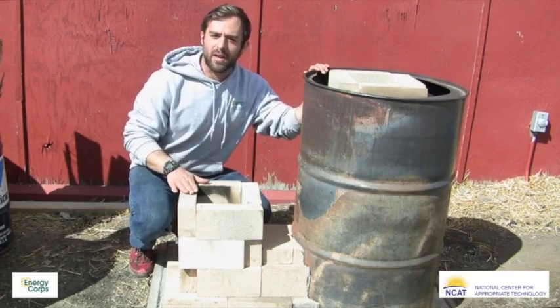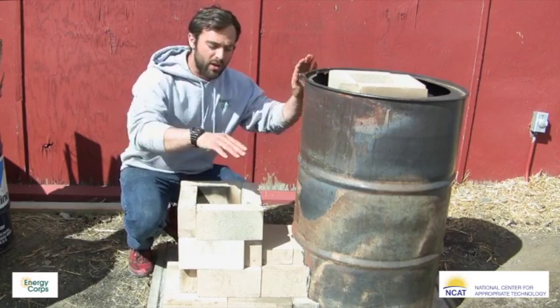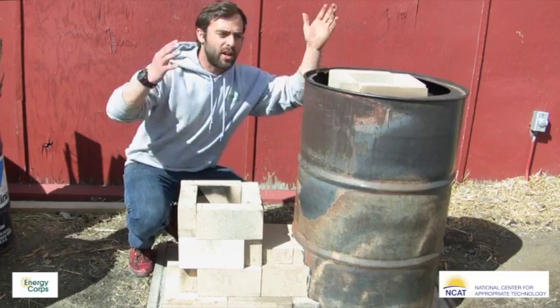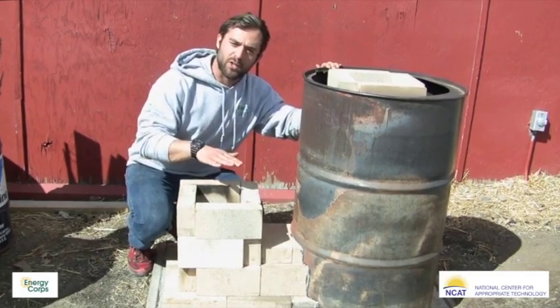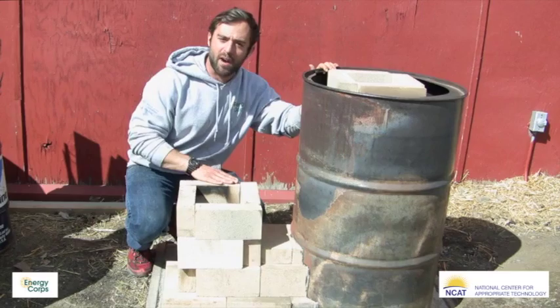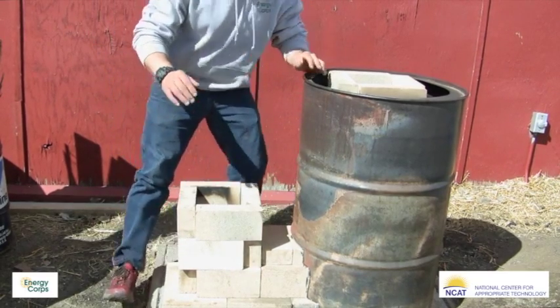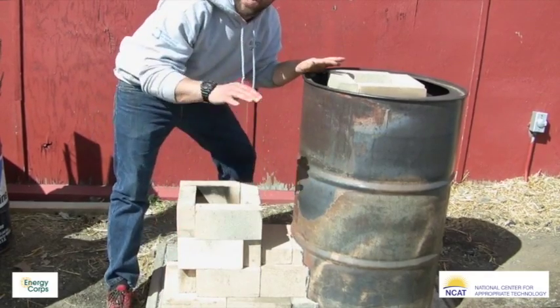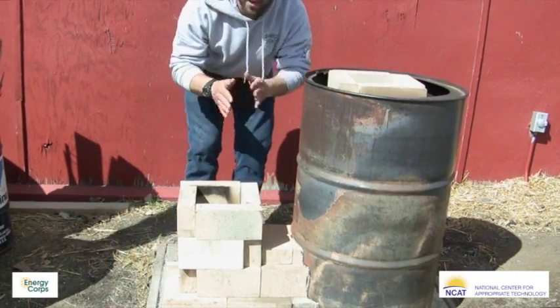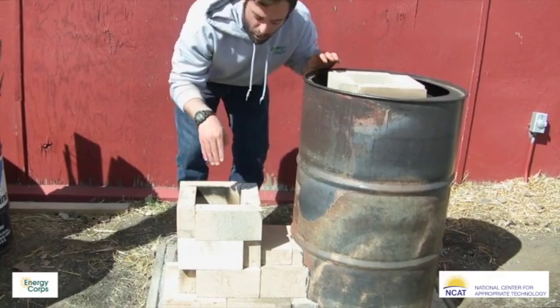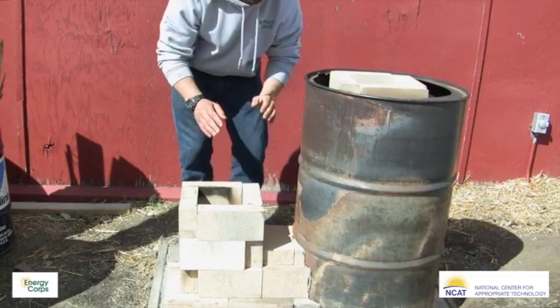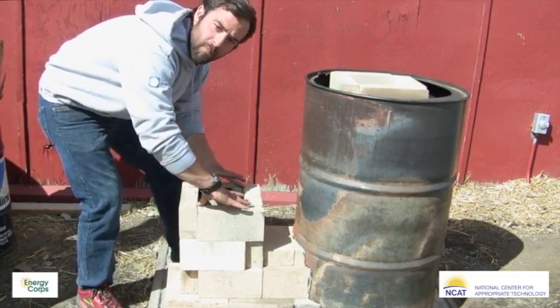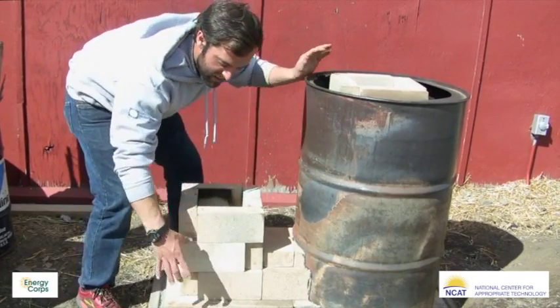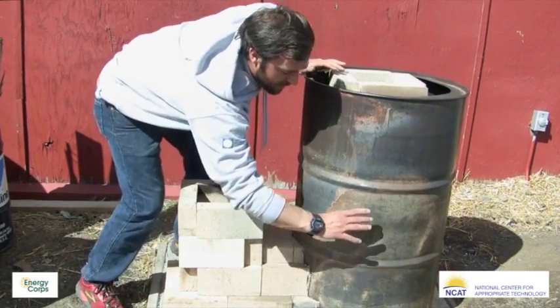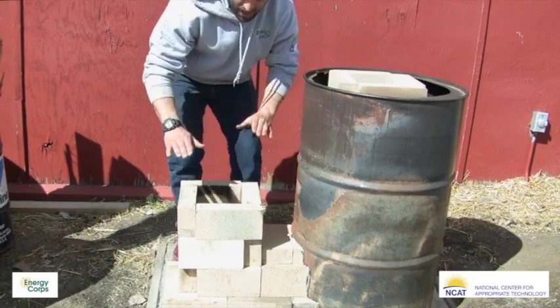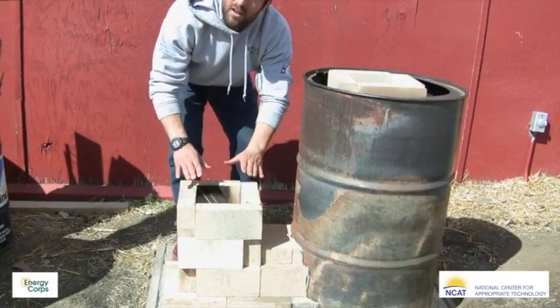So I want to explain how to build the rocket stove itself. First of all, you need to pour a level concrete slab at the bottom, because by the end of this, your kiln's going to be pretty tall, and you need a nice level surface to work with. As I mentioned before, you need 70 fire bricks, and these fire bricks, you're going to lay down one portion that's going to act as the very bottom of the rocket stove. You can't see it here, but the rocket stove features a burn chamber that is the exact same diameter all the way through. So the diameter here inside the intake is the same diameter all the way through and up the heat riser. This is the top portion of the heat riser, and it's the same diameter as this. And it's essentially this, but higher.